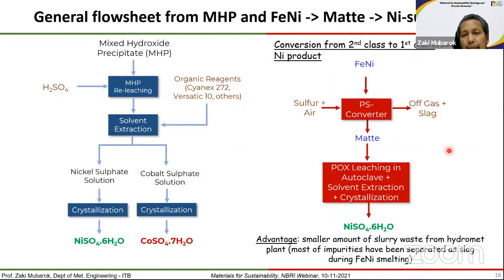And from MHP to nickel sulfate, cobalt sulfate, in general, the process is done according to the following flow sheet. Mixed hydroxide precipitate is dissolved in sulfuric acid or in ammonium-based solutions. And after that you do solvent extraction, multiple solvent extraction using certain organic reagents such as Cyanex, and others. Basically the solvent extraction is to separate the impurities from nickel and cobalt, and to separate nickel from cobalt. And after crystallization, then you get nickel sulfate and cobalt sulfate with water hydrate.